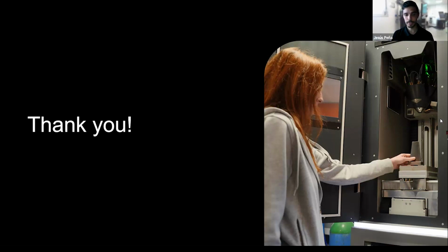Biomedical implants printed in the Meltio cannot have the really small size that you can, for example, make with powder bed fusion. What we do is for bigger implants, with a size of at least 2 centimeters. We can print them and focus on these applications, and you can get the actual properties and the actual oxidation that I mentioned before. That is critical for having a titanium grade 23.